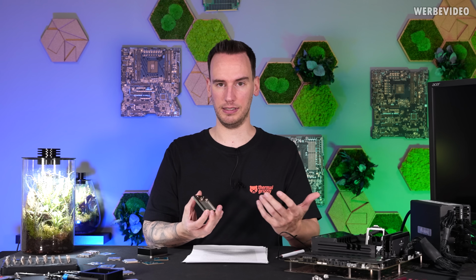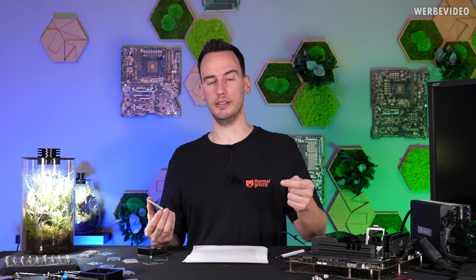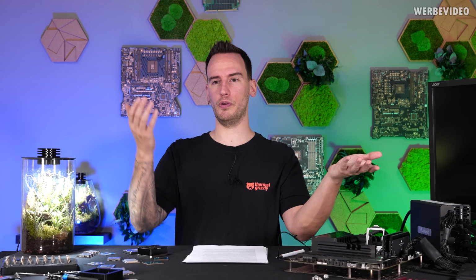In the end, our entire design, everything was fine from the beginning. It was just that we failed in our validation process, in our testing. That was also caused by one CPU dying during this validation process. If you have two 14600Ks, they will perform differently. They will have different temperatures, might be different by like 5 degrees or 10 degrees between two different CPUs. And we didn't test it fully again. We should have taken a second CPU, done the entire process of measuring without delidding and then delidding, and checked all the temperatures. Then we would have noticed that with nickel plating, the performance would be off. But we had without nickel plating on one CPU that died, and then with nickel plating on a different CPU, which was not comparable. And this is how we messed up.